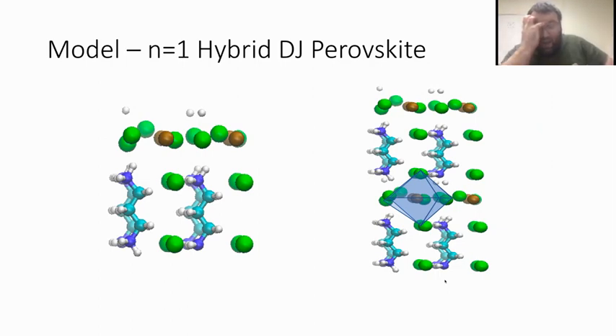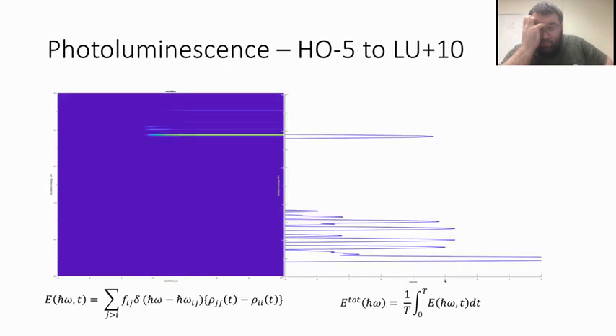If you could go to the next slide again. So here we're looking at the photoluminescence for the material, and this was calculated with an excitation from HOMO -5 to LUMO +10. And we see that there is an excitation, I cannot read that number, that begins around 1 picosecond at approximately 3.3 eV.